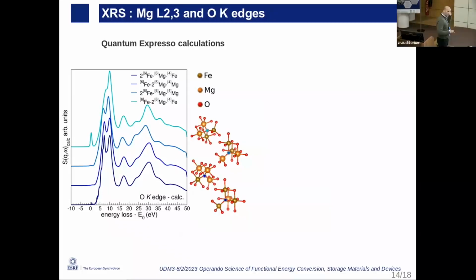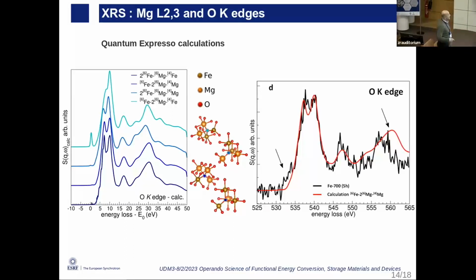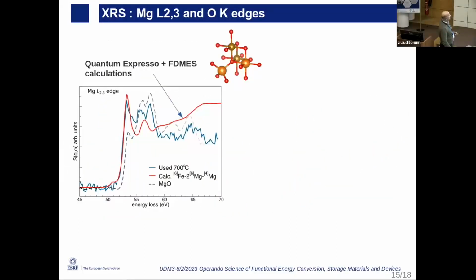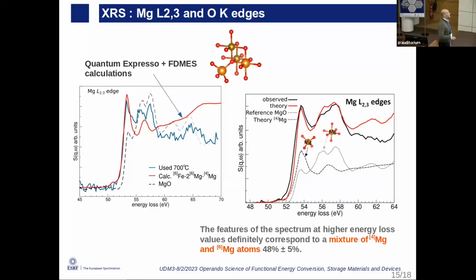So in order to prove that actually oxygen sees a tetrahedral environment, we did several relaxed structures with Quantum ESPRESSO calculations. We tried different configurations, but already you see from here that if you have the iron in octahedral condition that sees both magnesium in octahedral and tetrahedral condition, we have a quite nice reproduction of the data. So to complete the scenario, we need to study the magnesium. Of course, we again tried different structures, but the tetrahedral one, that one here, reproduces basically the main features of the main resonance peak. So then, by combining tetrahedral and octahedral environments, we finally could fit our configuration completely, and we could establish the amount of magnesium in the two different configurations as a function of the different treatments. So for the used material, we ended up with basically 45%, 48% of magnesium in tetrahedral.